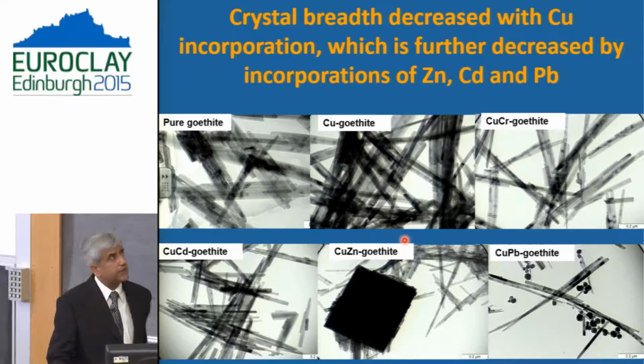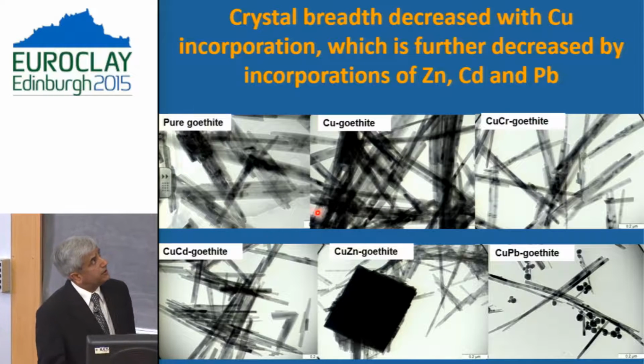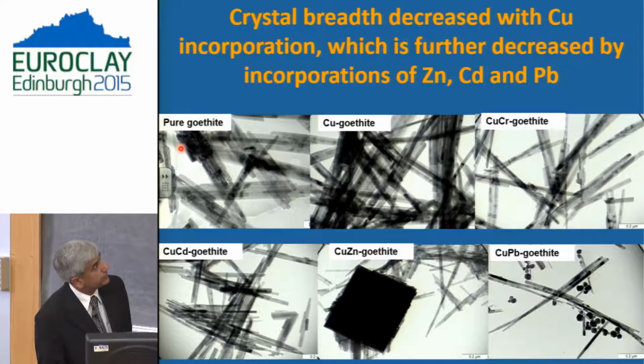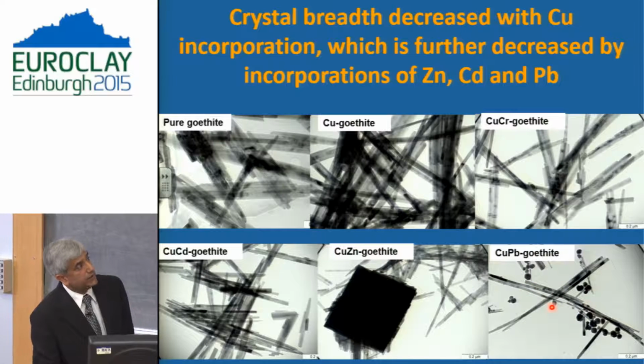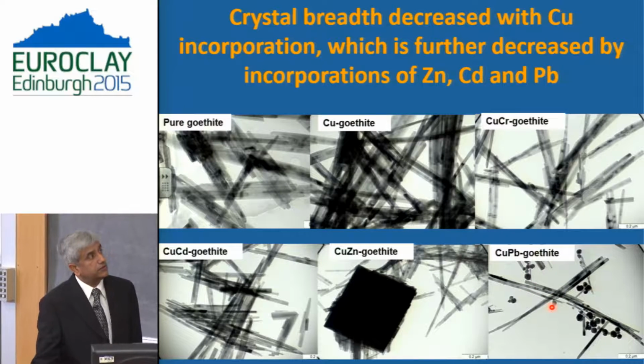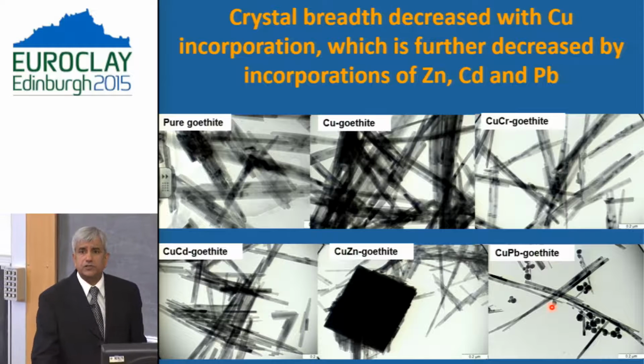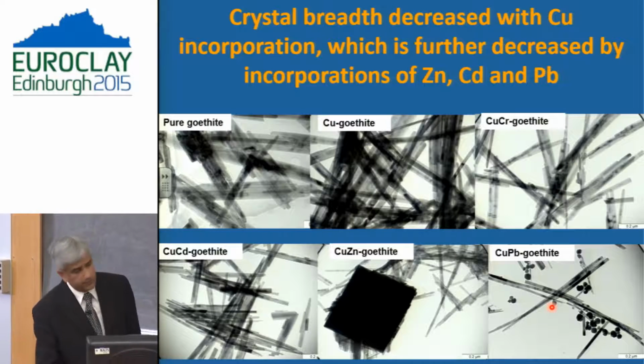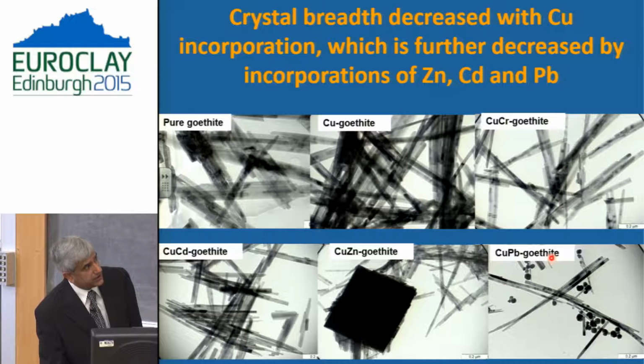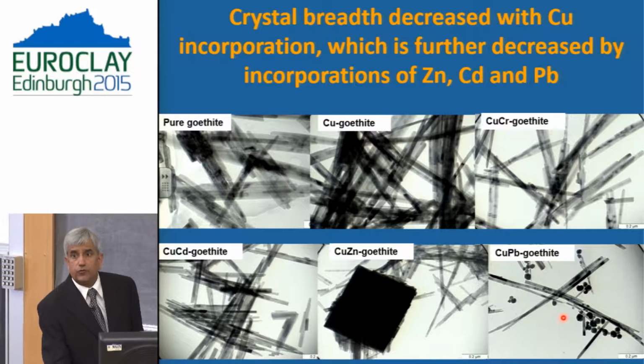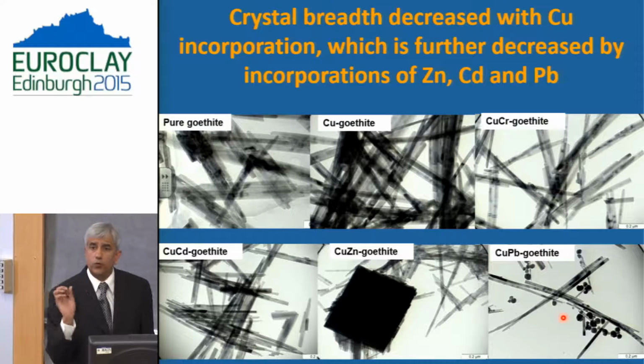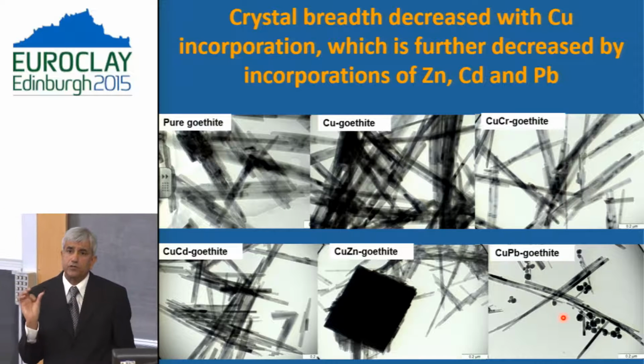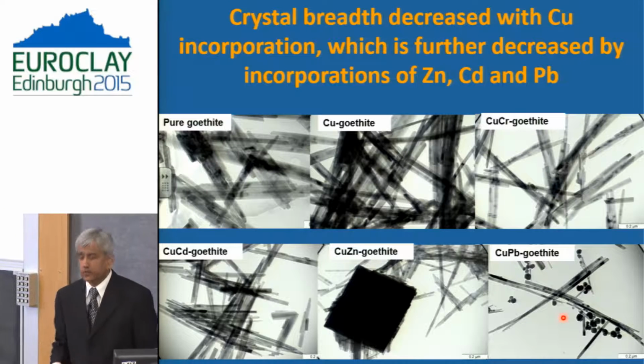That is once again demonstrated in the TEM micrograph of these samples. Once again, here is a pure goethite, and if you look at the copper and lead substituted goethite, you can see the crystals become much smaller, and sometimes you start seeing two different types of morphologies: some small sub-rounded, rounded crystals, as well as some acicular needle-shaped crystals.